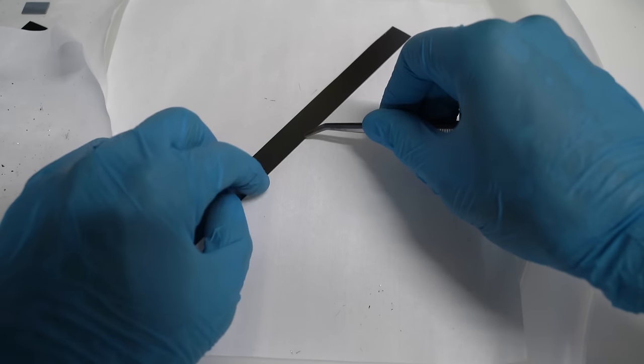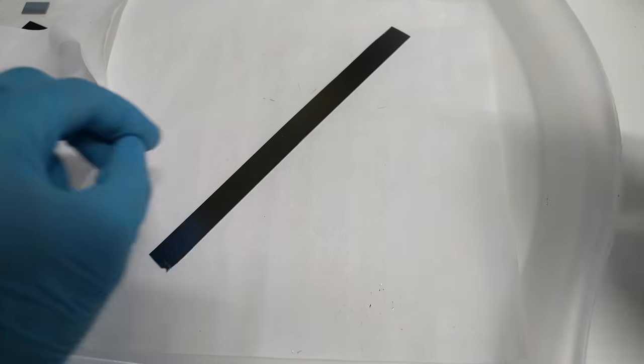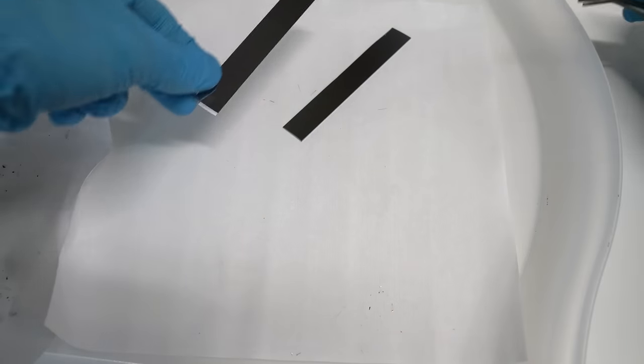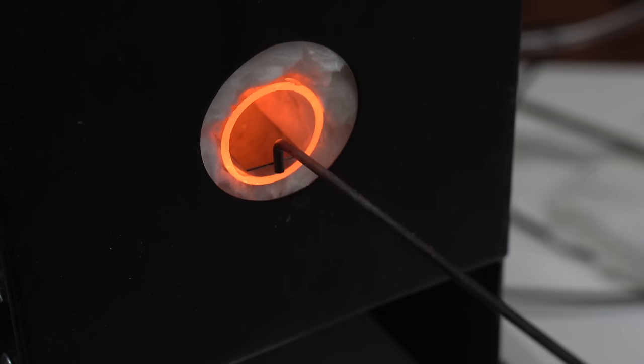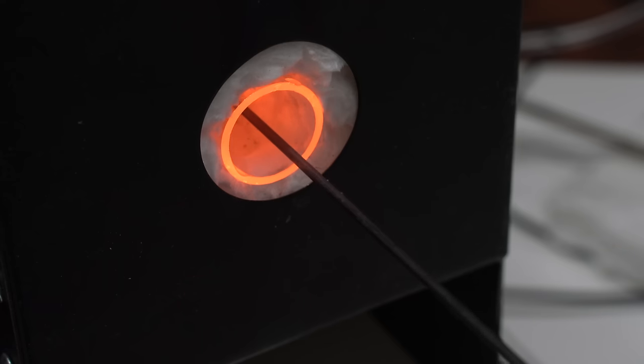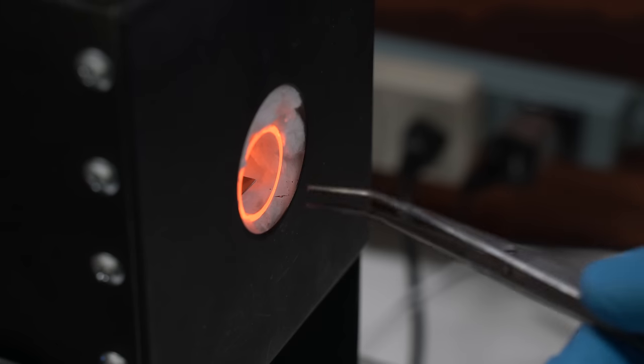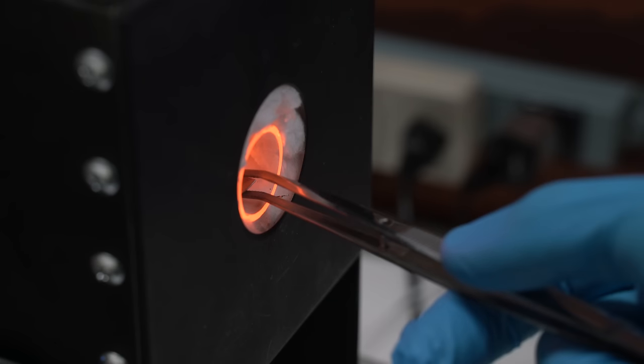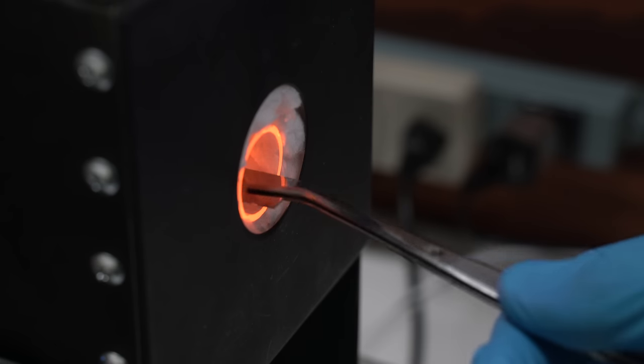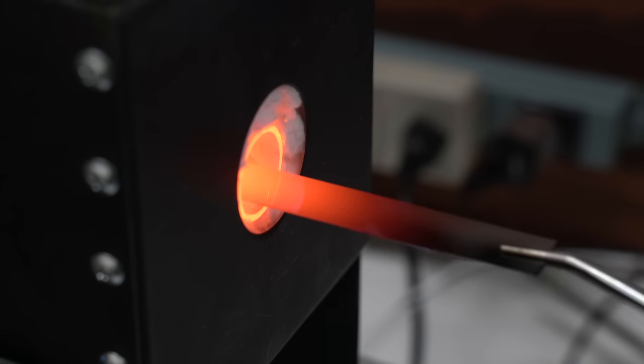If you want to estimate this for yourself, get a piece of silicon that is about 10 centimeters long, and carefully insert it into the furnace so that the edge of the wafer is directly in the center. The oxide growth rate will be fastest here, and it'll be slower as you move toward the other end of the wafer where the temperature is lower. You can clearly see the temperature gradient on the wafer as I pull it out of the furnace.